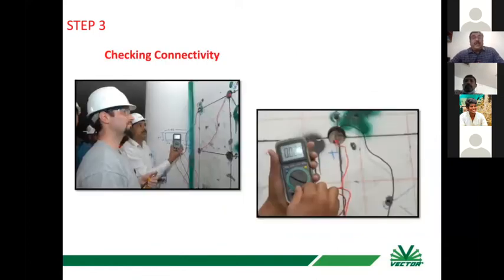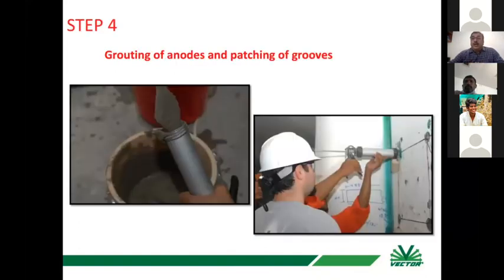We check the connectivity at all the levels, and the voltage should be less than 1 millivolt if they are properly connected. So you need to check the steel to steel connection in the concrete. You need to check the anode to steel connection in the concrete, and then seal the surface with the low resistivity mortar, and you don't see anything on the surface.